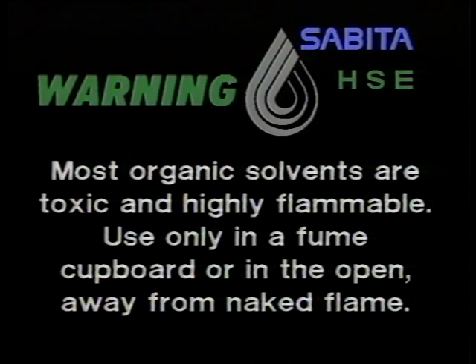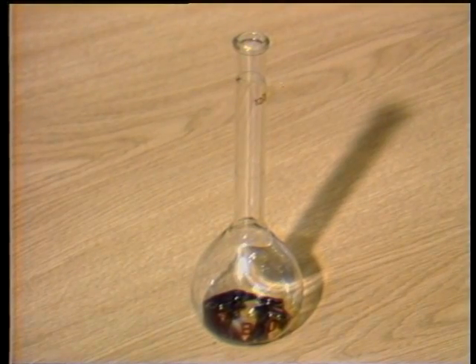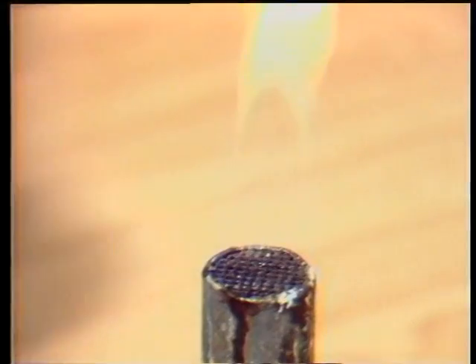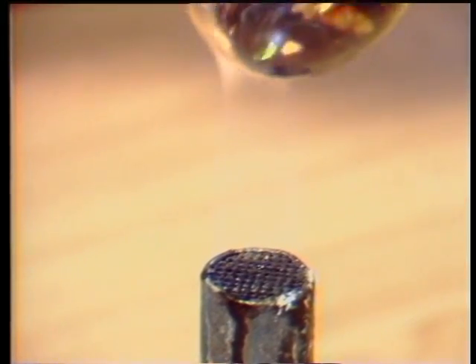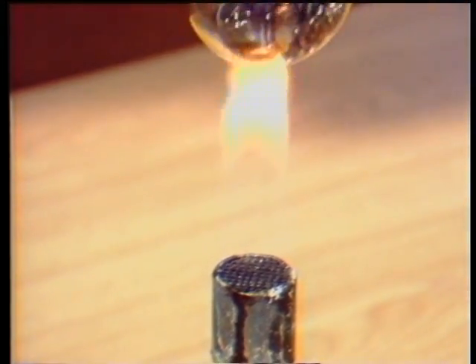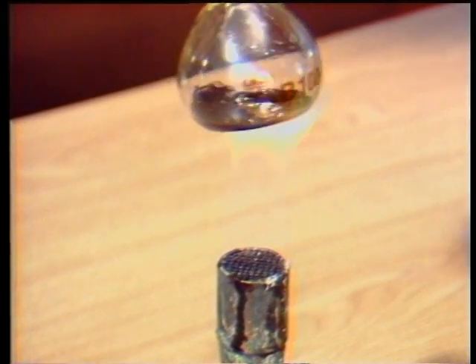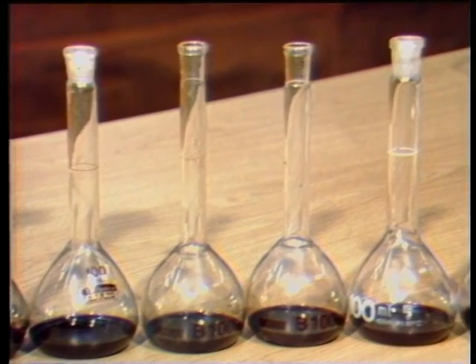Warning: most organic solvents are toxic and highly flammable. Use only in a fume cupboard or in the open, away from naked flame. Preparation of samples. Put 2 grams of the sample into each flask. Gently heat the sample over a flame or a hot plate so that the sample lightly coats the bottom of the flask. Allow the samples to cool to room temperature.